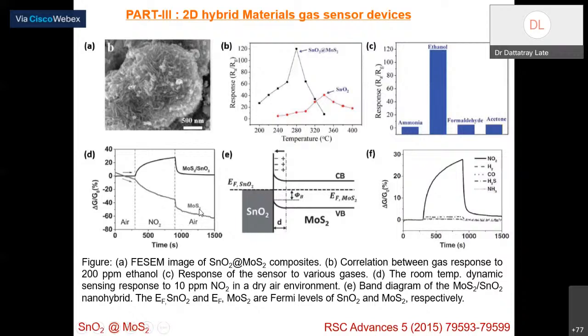This is the advantage. You can see this band structure, the MoS2 conduction band structure. The advantage is that when you coat SnO2 on the MoS2 material, there is good separation. This separation does not allow the SnO2 nanoparticles to be agglomerated. When the material is not agglomerated, it has a very high surface area, because a large surface area is available. Sensitivity and selectivity are parameters basically based on these properties of the material, such as surface area, because once a large surface area is available, you will get very high selectivity, sensitivity, and of course response and recovery as well.